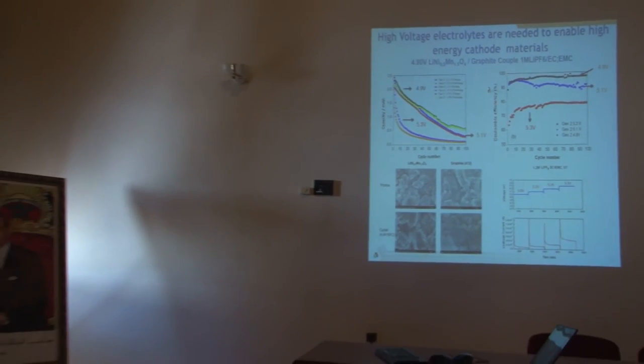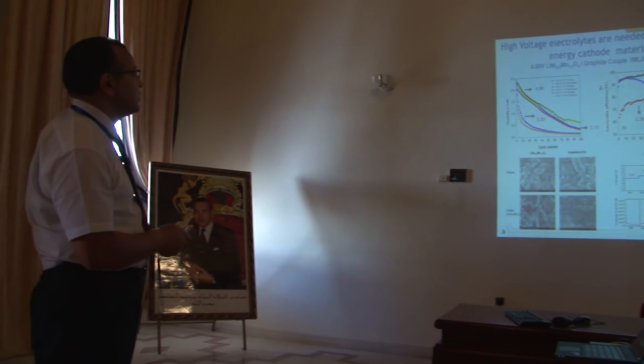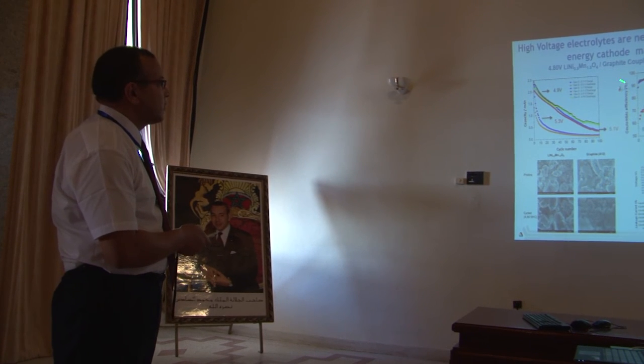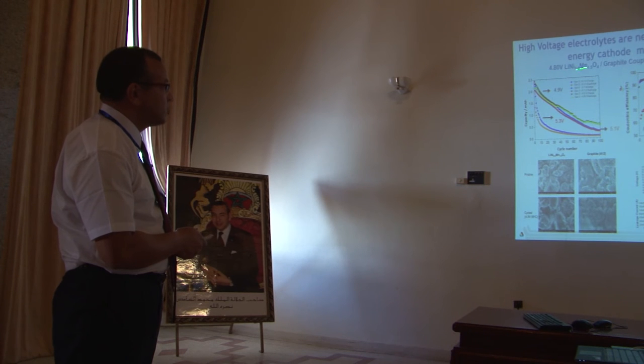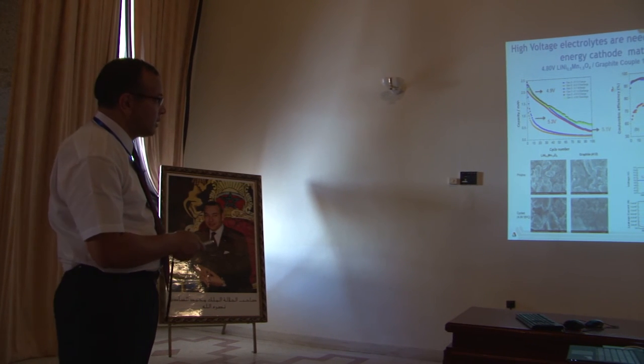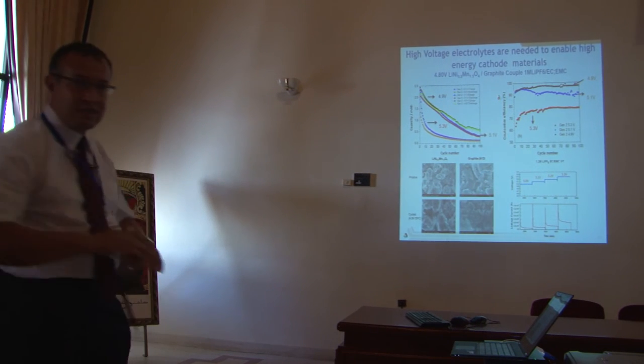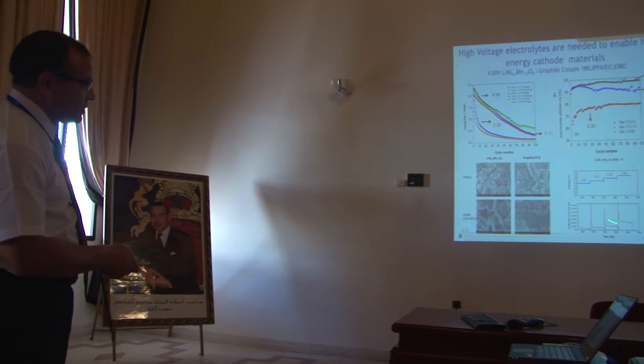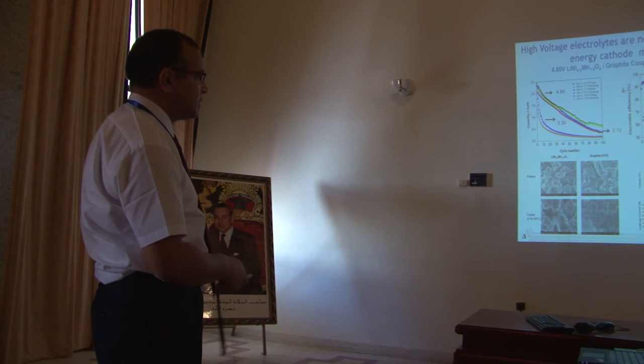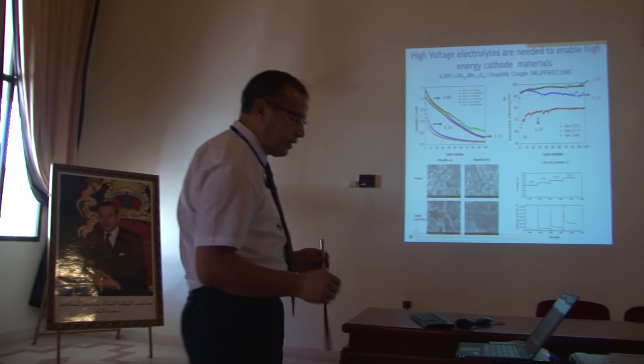Now, since we are operating at high voltage to get those high capacities, we have to look for high voltage electrolyte. I'm going to share with you one example of high voltage electrolyte that we developed. If you take a conventional electrolyte, a carbonate-based electrolyte, and operate at high voltage using this high-capacity, high-voltage cathode, you can see that the capacity drops very quickly depending on the voltage you use, and the efficiency is very, very low. I think the best example is using a floating test. You take this cell and float it at a certain voltage and look for leakage current. Of course, leakage current means decomposition of electrolyte. So at high voltage, you have a high leakage current, as you can see here. So clearly, conventional electrolyte in the long run might not work under high voltage operation.